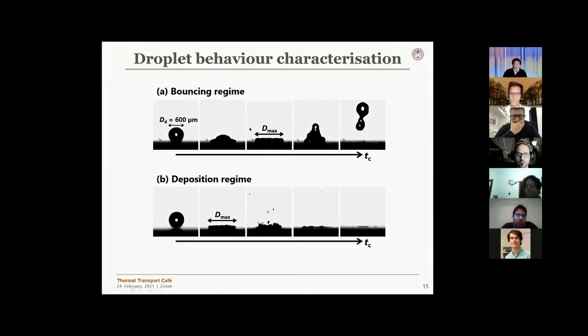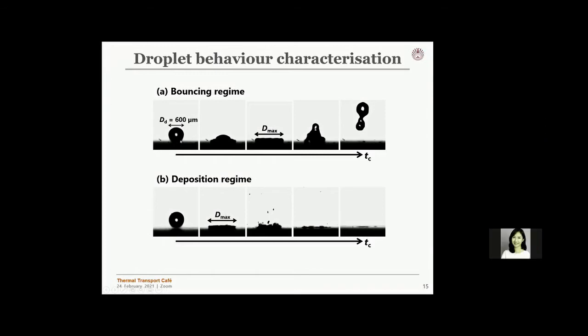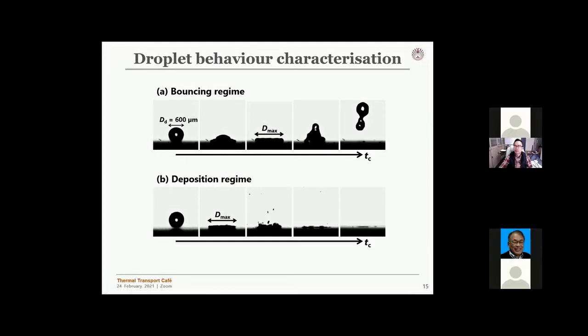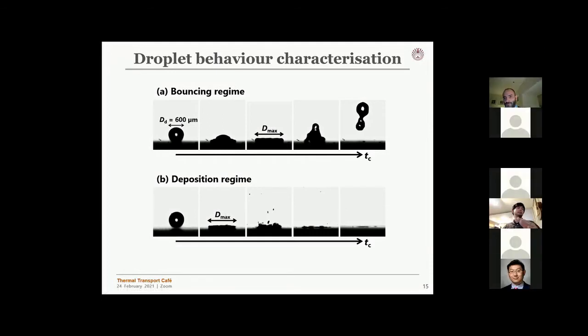This bouncing is basically due to the film boiling regime. If you lower the temperature, the bouncing regime ends and the droplet stays in contact on the surface until it evaporates away. So we classified droplet behavior into two regimes, and measured the maximum droplet spreading diameter as well as the contact time as characteristics of droplet behavior.